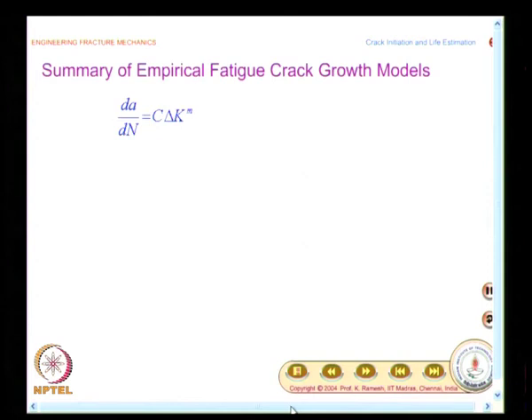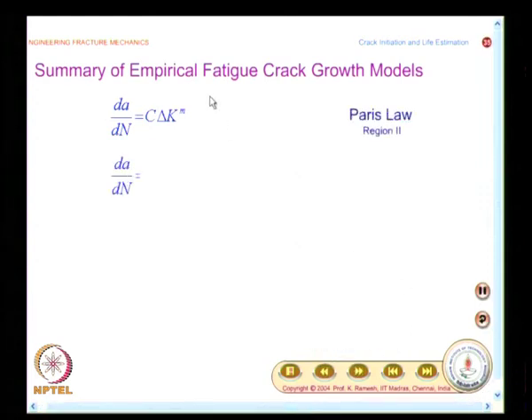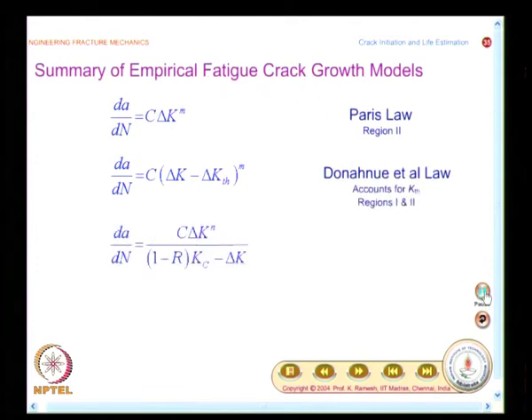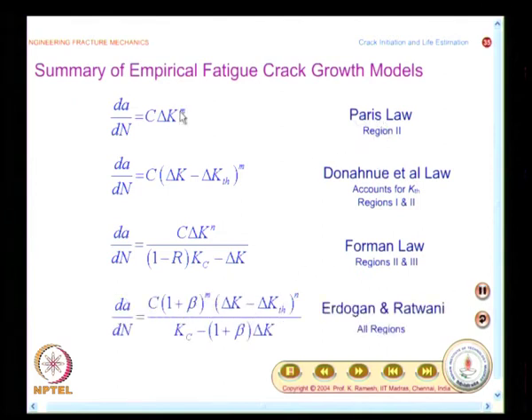And what we will see is, in summary, let us look at what are the empirical fatigue crack growth models we have seen so far. We have seen Paris law, which is the simplest. You have dA/dN equal to C delta K power m. Then we had seen Donahue et al. law, which accounts for the K threshold, that is regions 1 and 2. This is given as dA/dN equal to C into (delta K minus delta K threshold) whole power m.